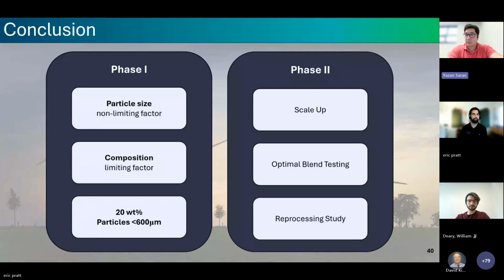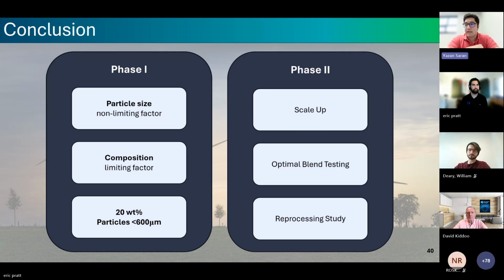Phase 2 included our scale-up trial, where we received and blended a 50-pound bulk sample of 16 weight percent cross-linked polyethylene and polypropylene, shipped that bulk sample to Prysmian for them to perform their industrial scale compounding and pelletization trials, and then shipped our pelletized blend to our injection molding partner, Vandor, delivering on our primary deliverable of a functional molded spool. We also then proceeded to test our optimal blend in-house and performed our reprocessing study.